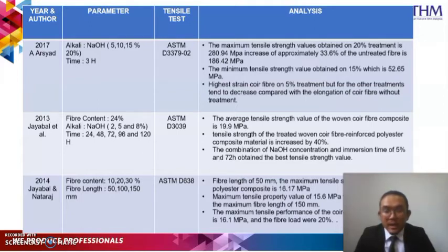In 2014, Jayabalan and Nataraj found that at a length of 50 mm, the maximum tensile strength of coir fiber polyester composite is 16.17 MPa. The maximum tensile properties value of 15.6 MPa was obtained only for the maximum fiber length of 150 mm. The maximum tensile performance of coir fiber polyester composite is 16.1 MPa and the fiber load was 20%.